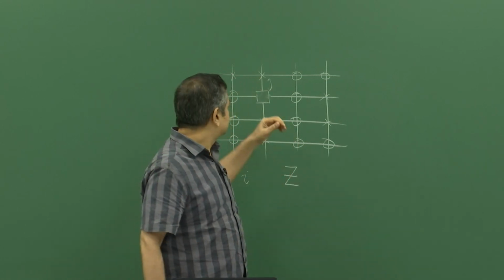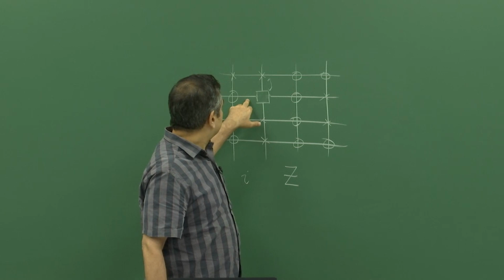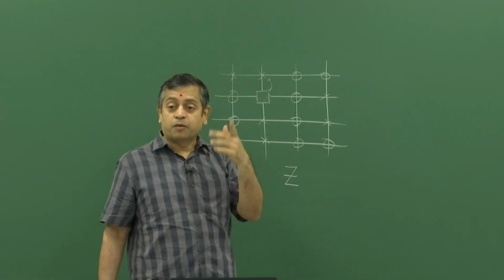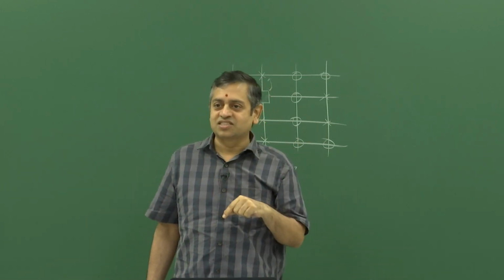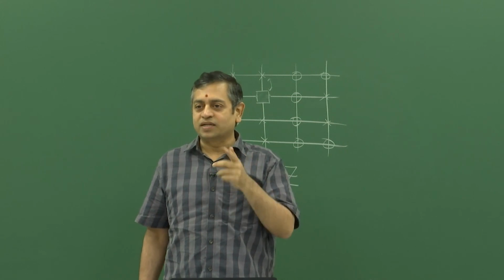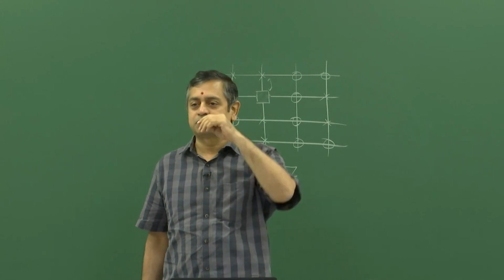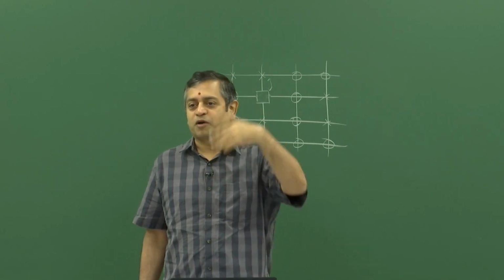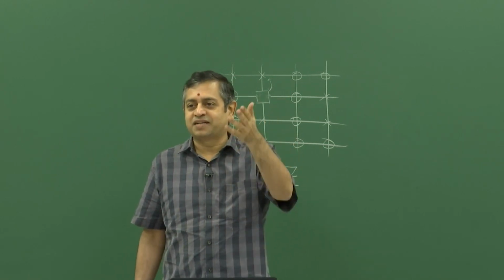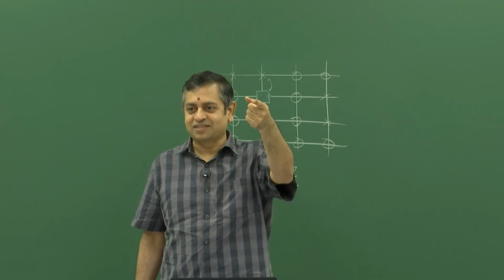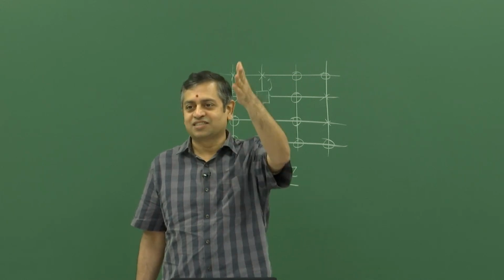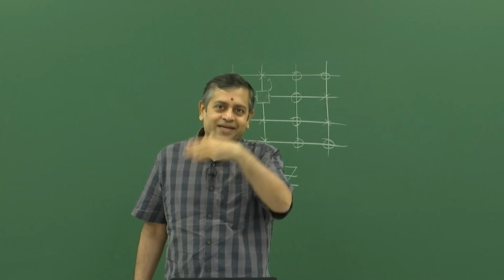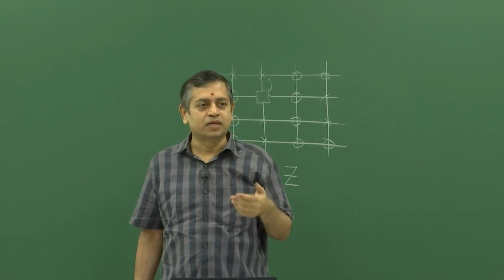In other words, statistically, the probability of having a neighbor as a vacancy is skewed once an atom jumps and the vacancy jumps next to it. So, now this atom has definitely more of a probability of seeing a vacancy, because it just made an exchange with the vacancy. So, it has certainty that there is a vacancy there. So, it tends to go back again, and it keeps doing this back and forth.